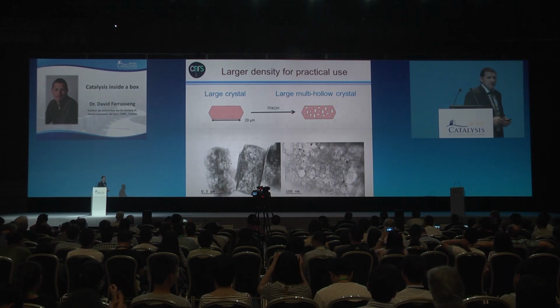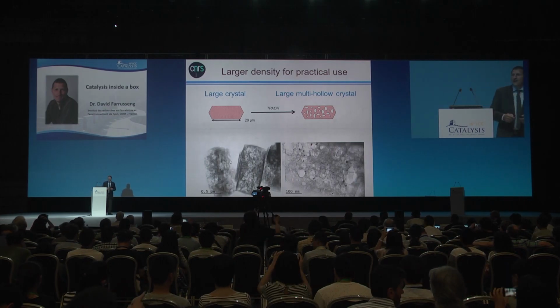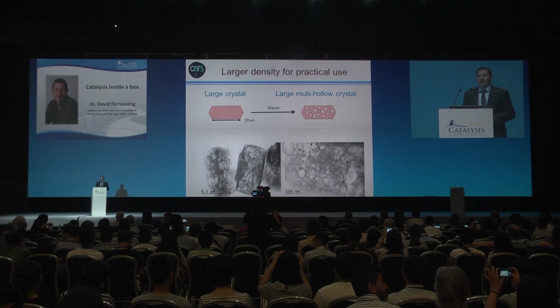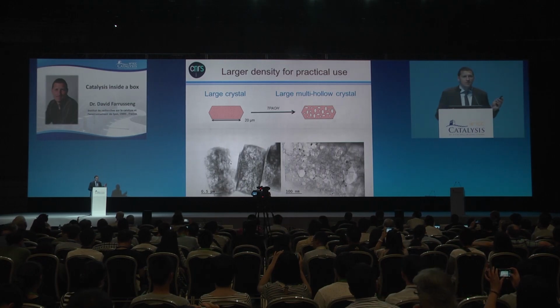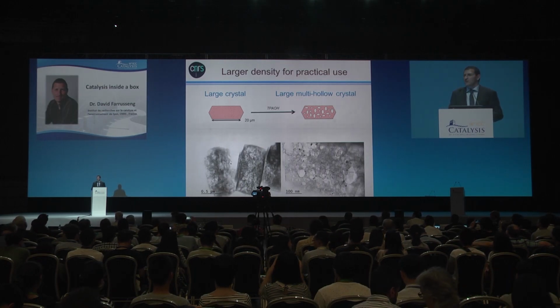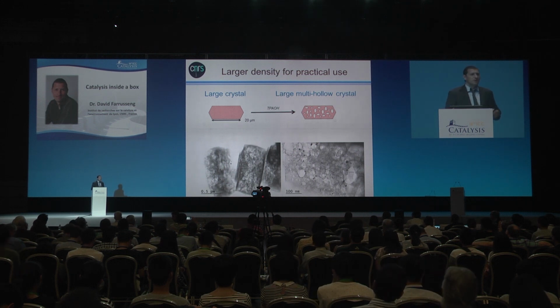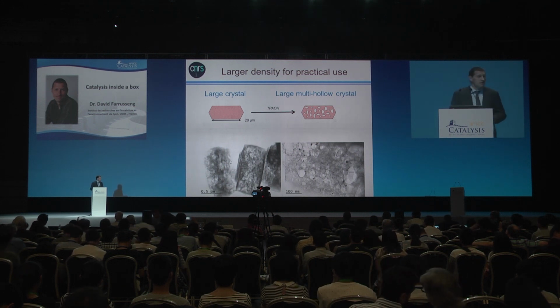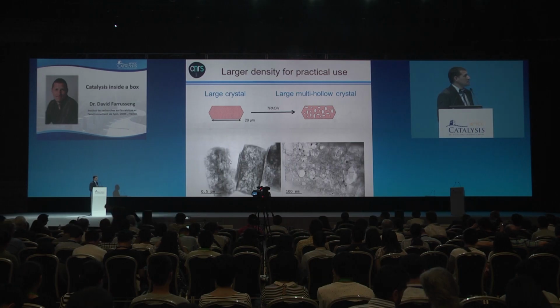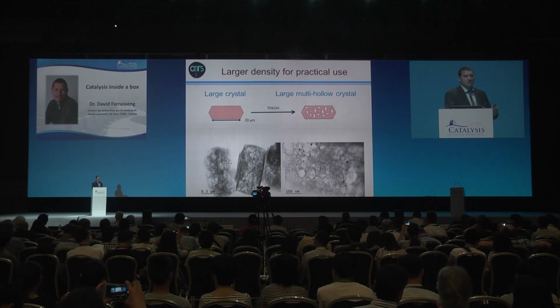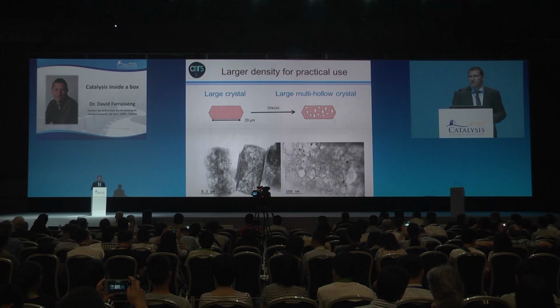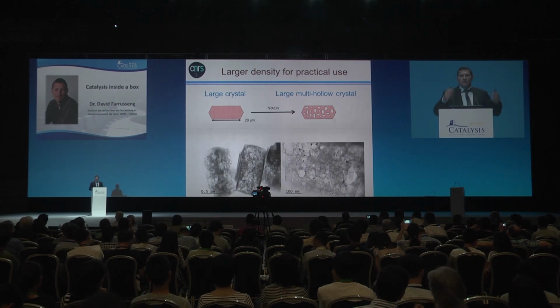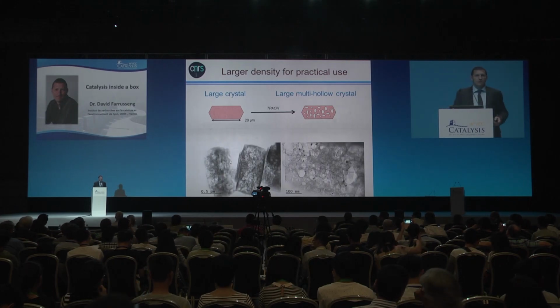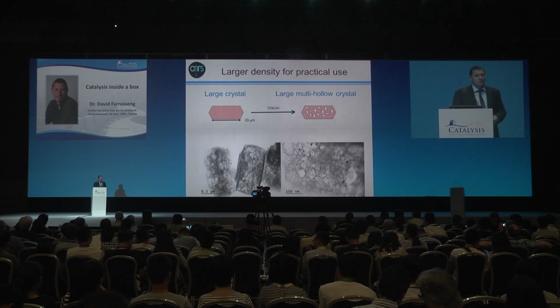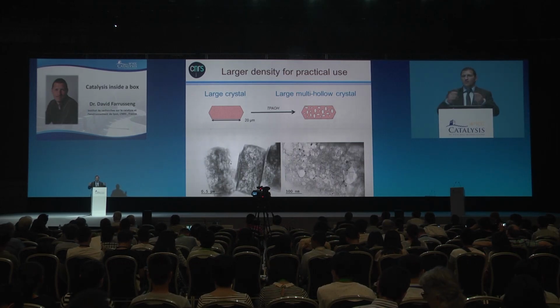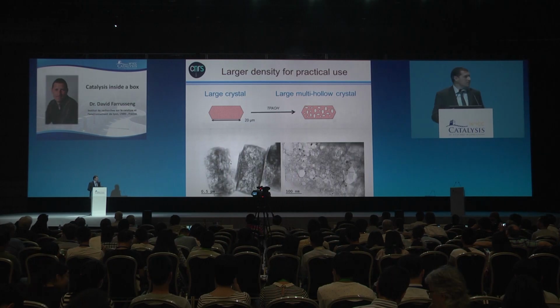I would say that despite so many advantages, I don't think I will see one day this system widely applied in the industry. There are many reasons, but one reason is the density of the metal particles per unit of volume, because it's just void, I would say. If you would fill a reactor with those hollow zeolites, it's just air, it's empty.